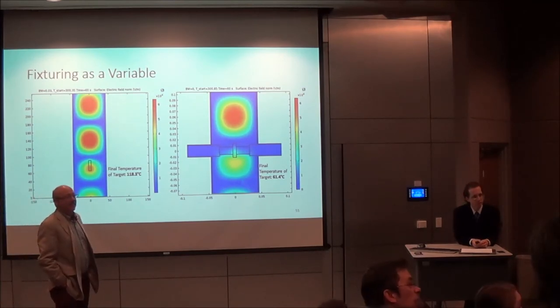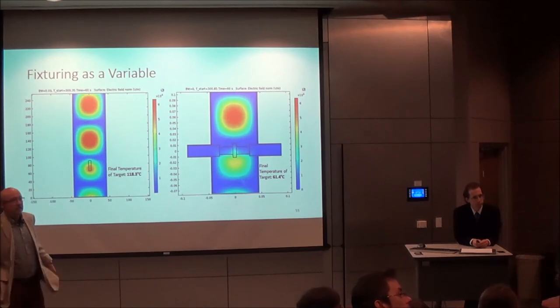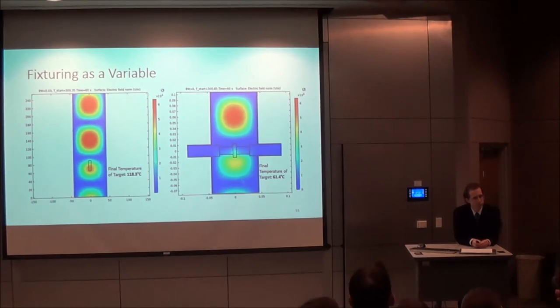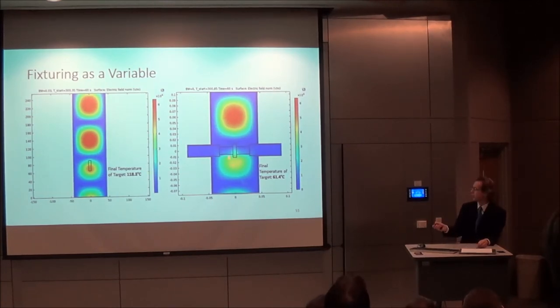Have you thought about perhaps having two generators, one on each side, that could project in some sort of cross configuration, and then you could make sure that you have the hot spots on both sides? It's not quite that simple. The wave is able to reach the other side. It's not fully reflected, but the reason there's a high intensity is because there's actually a back reflection on this pressure fixture, and it's kind of a superposition of peaks. And so adding another generator on the other side wouldn't actually give us any further advantage except being able to apply more power. Does that answer your question?